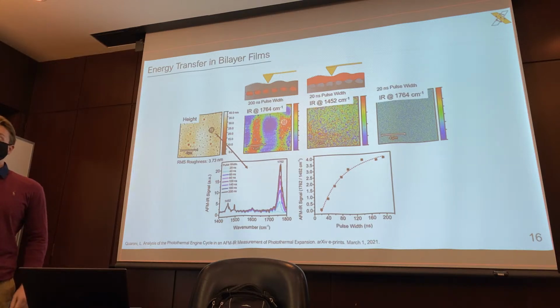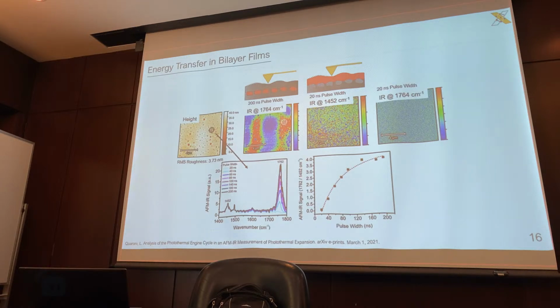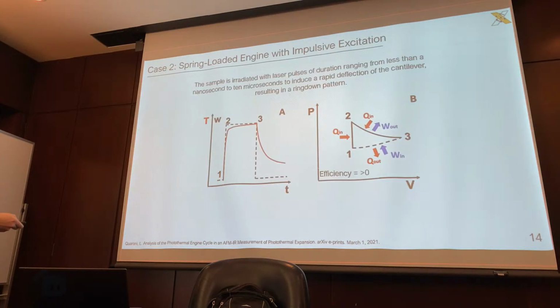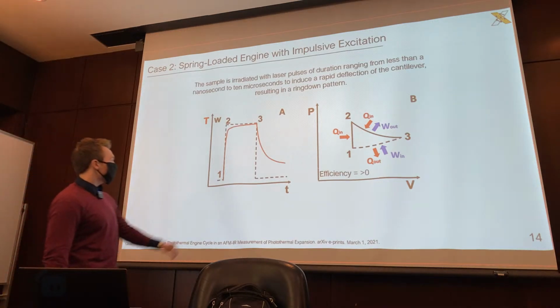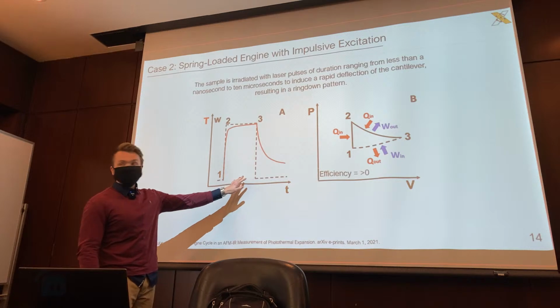Changing the pulse width, as I mentioned before, actually affects how deep we can detect this thermal expansion occurring, because we know our laser is going directly through a material. I mean, these are a few hundred nanometers in thickness. Infrared light is going to go right through them. But it's the thermal energy and expansion that we're trying to detect. Now, if we reduce our pulse width, which again is the width of how long the laser is on, in terms of this distance here is called your pulse width.